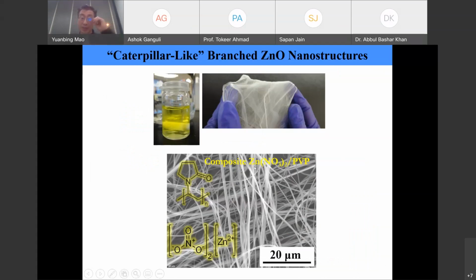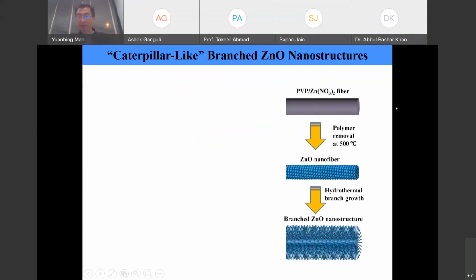Of course, to get these fibers, we cannot spin zinc nitrate aqueous solution directly, so we need to add a polymer into it. Here we use PVP as the binder. So we get these fibers, and then the next step: normally, we know this process, if we want to remove the polymer, we burn it, and that's what we did. At the same time, we are able to keep the nanofiber shape while we convert the zinc nitrate into nanoparticles.